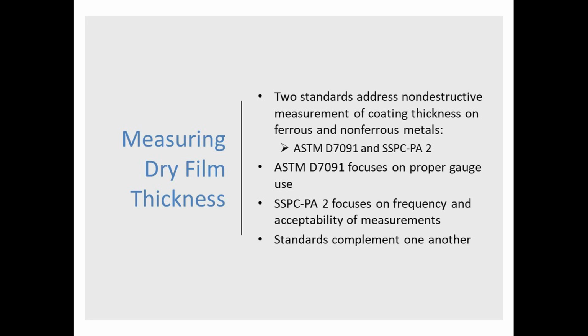Measuring dry film thickness, something that we all are pretty familiar with probably, and it's interesting to me that as chair of the SSPC committee on dry film thickness, taking a dry film thickness measurement with an electronic gauge is remarkably simple. But it's everything else that gets really, really involved. How many readings do I take? How do I make sure this gauge is even working properly first? So really that's the basis for this ASTM standard and the SSPC standards, to make sure these gauges can be used properly.